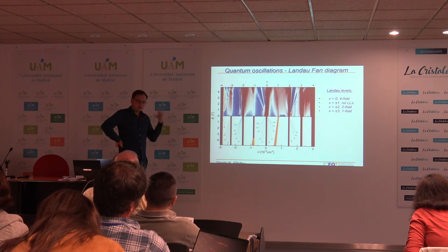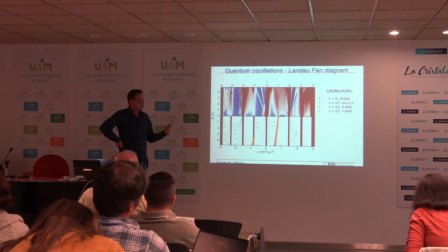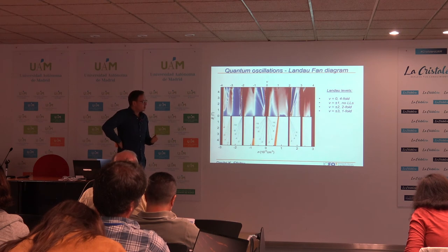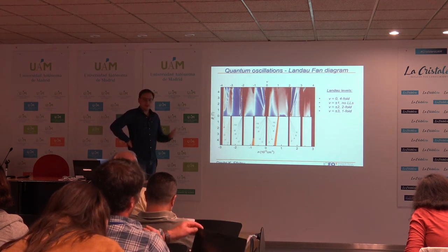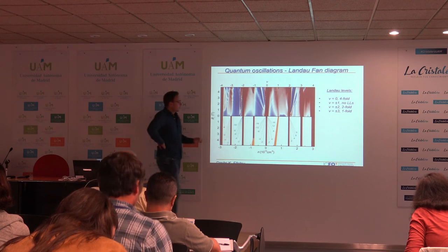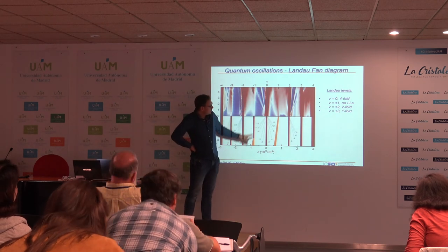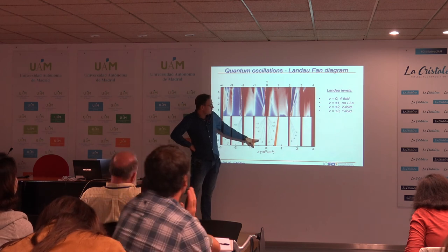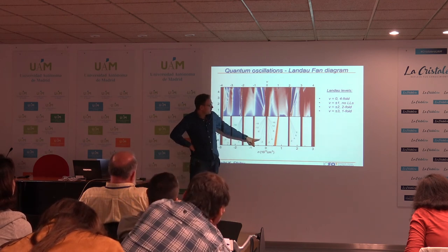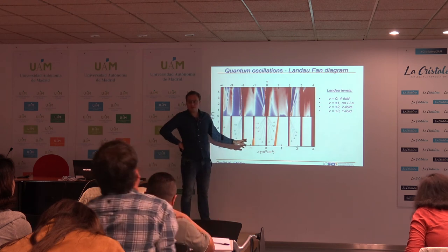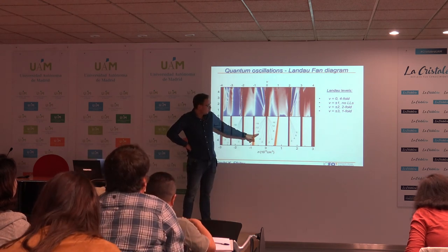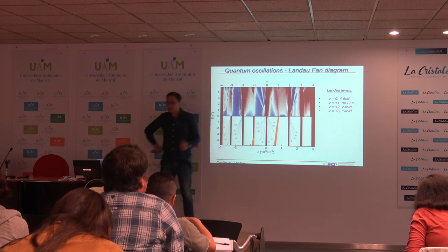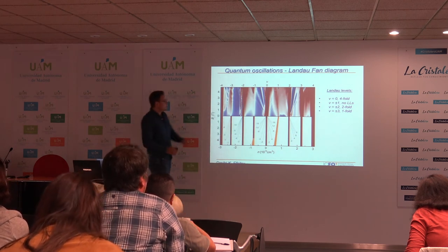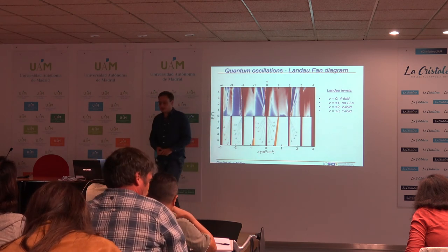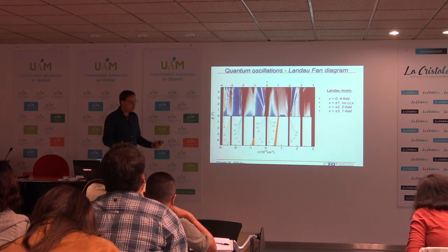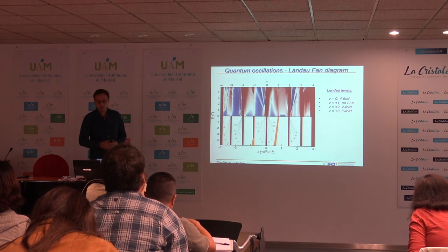Is this four electrons, like for a valley and spin unpolarized state, or is it maybe less than these four electrons? So indeed, we can now look at these slopes here, and at charge neutrality we usually get a sequence where we really see that all of these Landau levels are fourfold degenerate. So we get sequences of minus 4, minus 8, minus 12, minus 16. And this tells us that what happens to these bands closest to charge neutrality is that they should not have K or spin degrees of freedom broken.